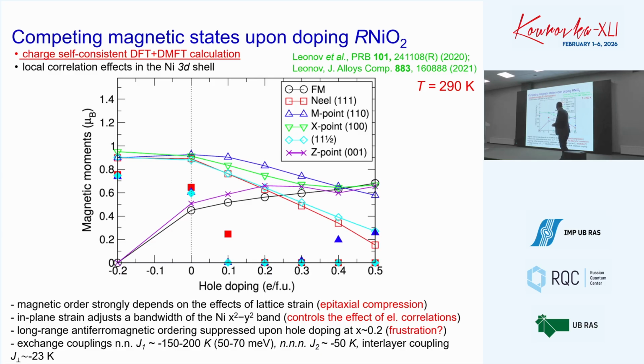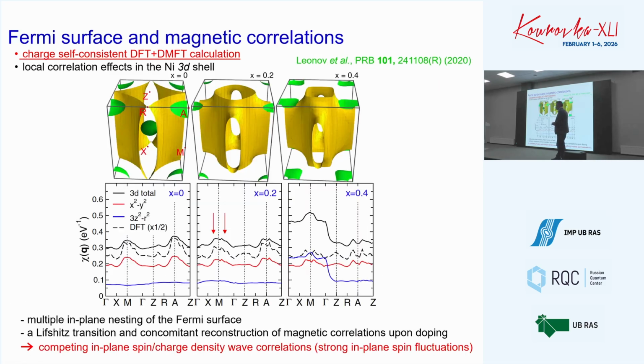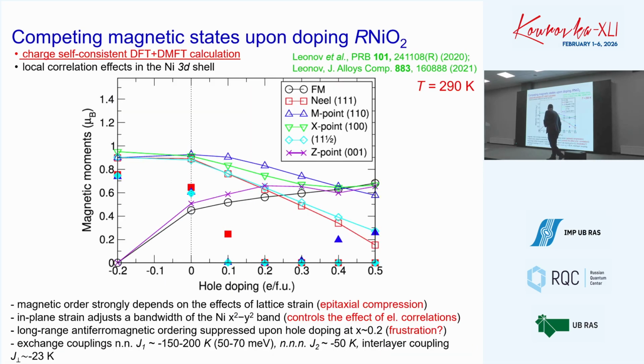What we end up with is some kind of magnetic phase which drastically dropped upon some slight doping to 0.1 holes. And this is like a room temperature calculation. We tried to go down to I think less than 100 K. We didn't manage to find any magnetic state here, just at the optimal doping. Although upon large hole doping, there is a transition towards the M state, some kind of planar antiferromagnetic ordering, like we received in our susceptibility calculations.